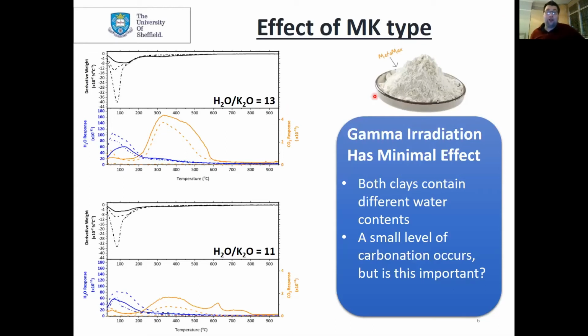This is for the rotary calcined white metakaolin. What happened with these samples is that fundamentally they lost water under irradiation, which was to be expected. The dashed dot line here is a room temperature sample, the solid black line is the sample that went in the irradiator, and the dashed line in the middle is a sample heated to 50 degrees C, the same temperature the sample undergoes in the irradiator. So it's fairly safe to say we've lost water here.